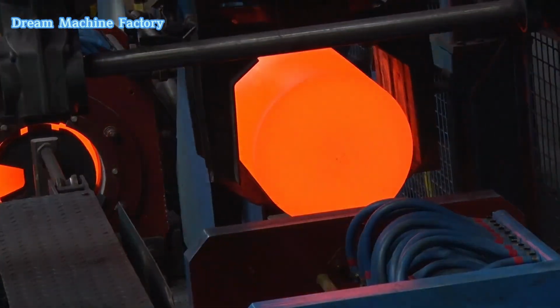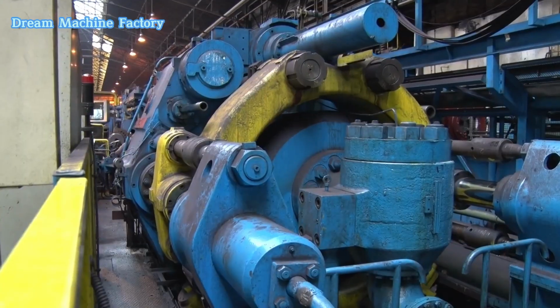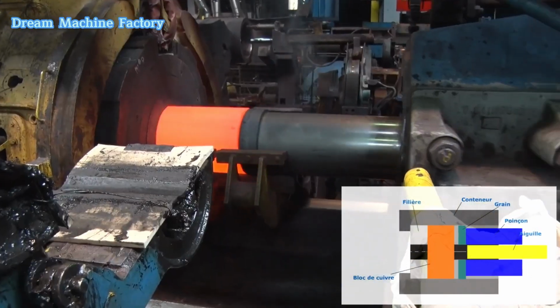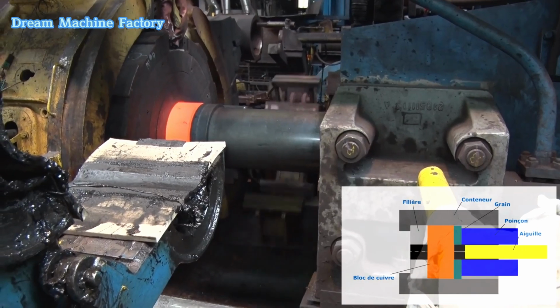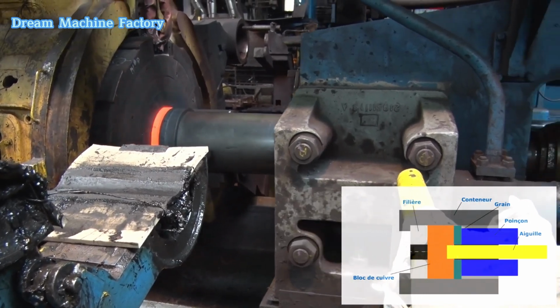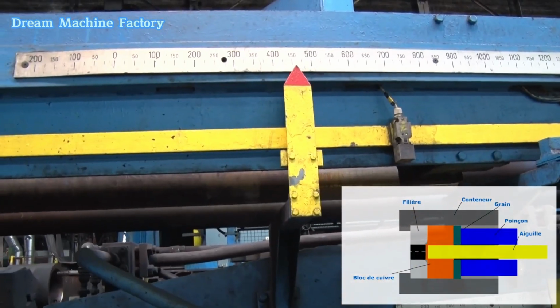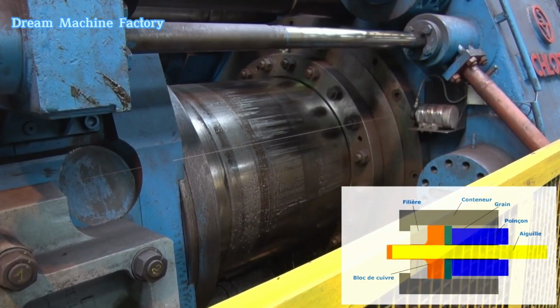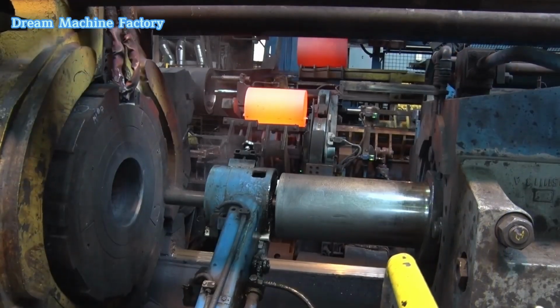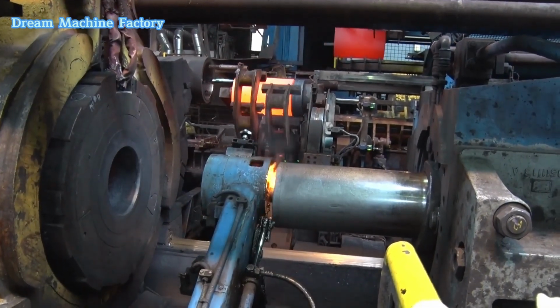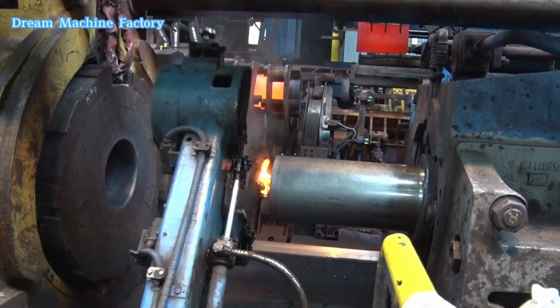The result is a significantly longer tube, often exceeding 120 meters in length. The tube then goes through a drawing process to achieve its final dimensions. It is pulled through a die and over a floating mandrel that precisely shapes the outer and inner diameters. Depending on the diameter, drawing speeds can range from 800 to 1,000 meters per minute.